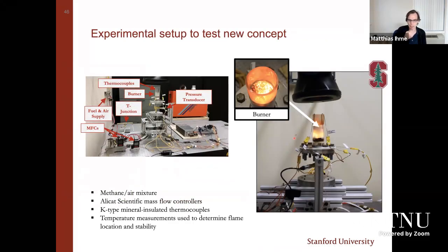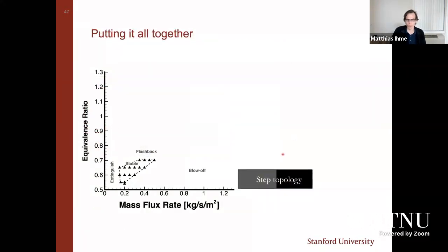And the last test that I want to show you before I close is the burner testing. Remember, we set out to demonstrate an extended flammability limit, an extended performance behavior of this additively manufactured porous media burner with tunable structures. One of the main conclusions from this analysis is that if you're using a step topology, you're getting a rather benign stability limit using this additive manufacturing process.